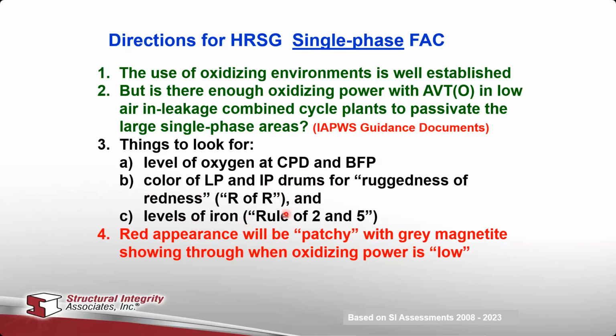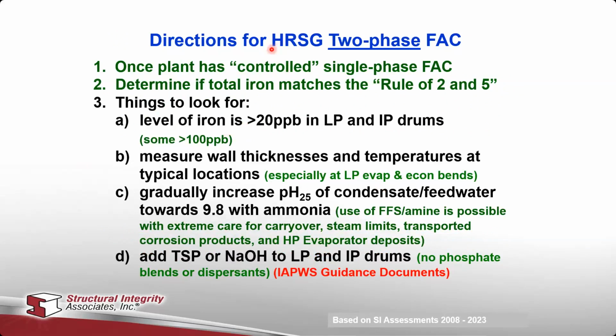And when you monitor the iron, you want those to be less than 2 ppb at the feed water and less than 5 in the drums. These are the key things for single phase FAC, and these are some of the similar things for two-phase FAC.